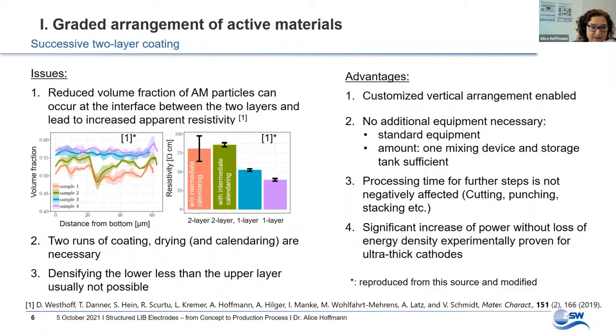Nevertheless, the successive two-layer coating enables a customized vertical arrangement of active materials. It does not necessarily demand additional equipment, and further processing steps like assembly time are not affected. And as it was shown, a significant increase of power without loss of energy density can be reached.